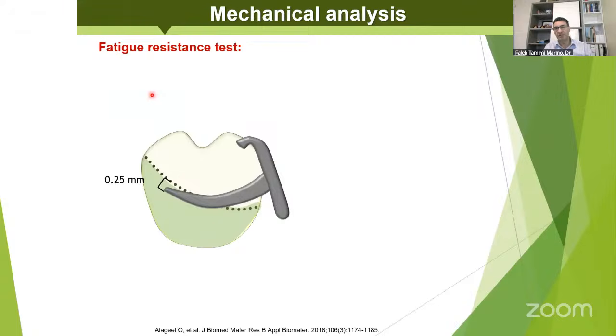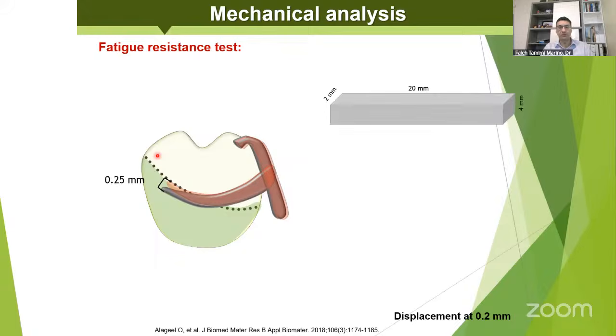Okay, and this became very apparent when we were testing fatigue, resistance to fatigue. So to do that, we tested, for example, what happens when a clasp in a partial denture is engaged in an undercut, it bends a little bit, right? So if you do that many times, it's going to bend a lot of times. And if the metal is not good, the metal is going to suffer from fatigue and it will become loose over time.